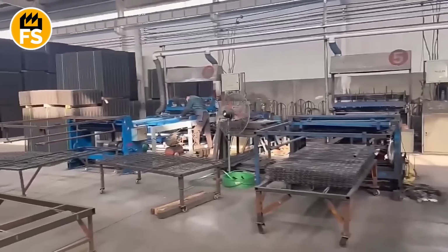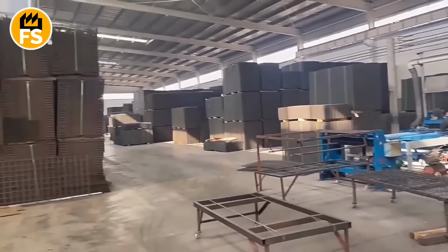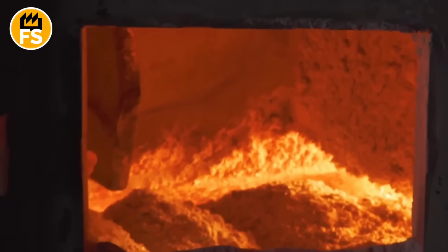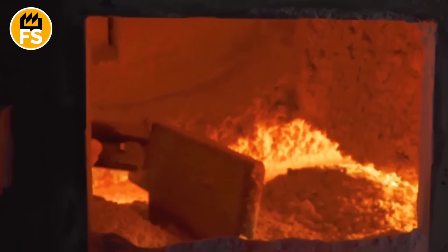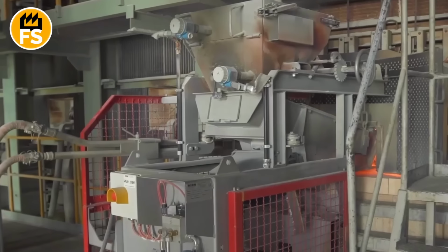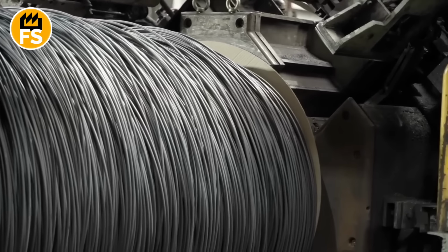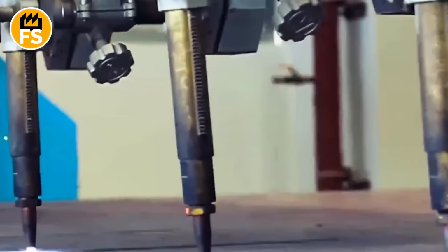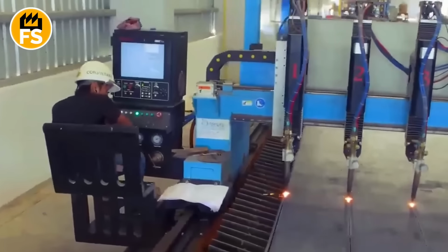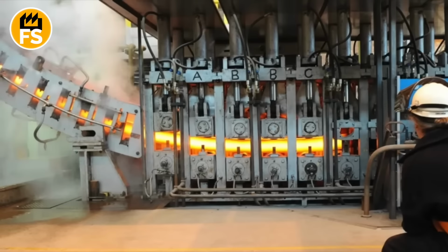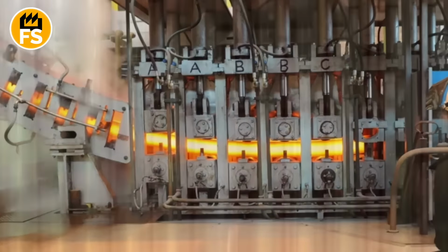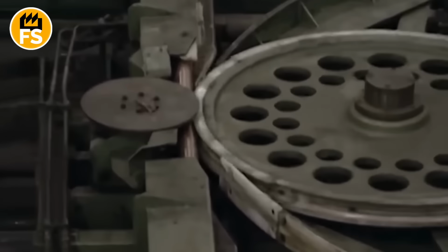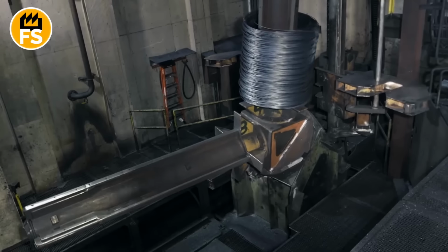To release this stress, the wire passes through a special thermal furnace. It's not visible from the outside. It's a long metal tunnel structure, inside which the temperature reaches over 1,000 degrees Fahrenheit. In such heat, resembling the middle of a bonfire, the wire slowly moves through the furnace, either lying on moving rollers or suspended. It gradually heats up to the required temperature and then slowly cools down. The whole process takes anywhere from a few minutes to an hour, depending on the thickness and grade of the steel. To the touch, the wire after this stage is just as smooth and shiny, but it no longer breaks.